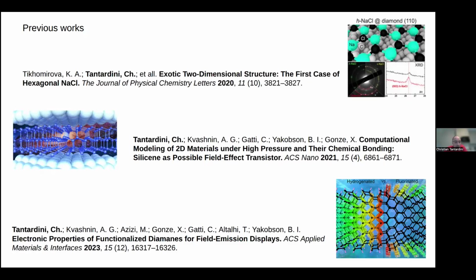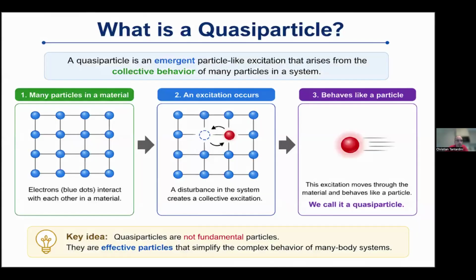And about functionalization, we have seen with Yakobson at Rice University that specifically when we have these diamanes, for example, and we change the termination from hydrogenated to fluorinated, we have an effect that can be more like a bulk effect or like a surface effect. So actually, previous work was done.